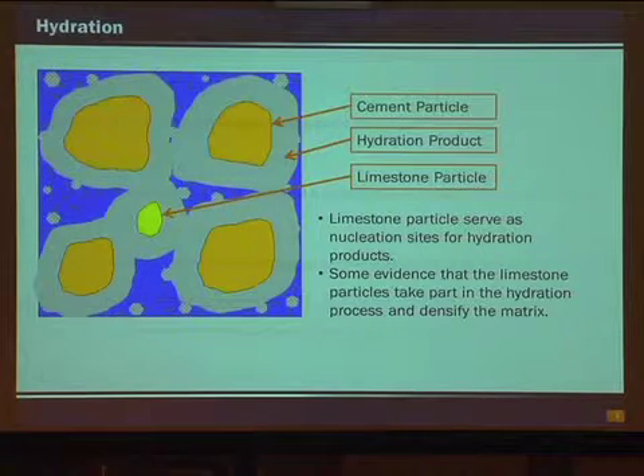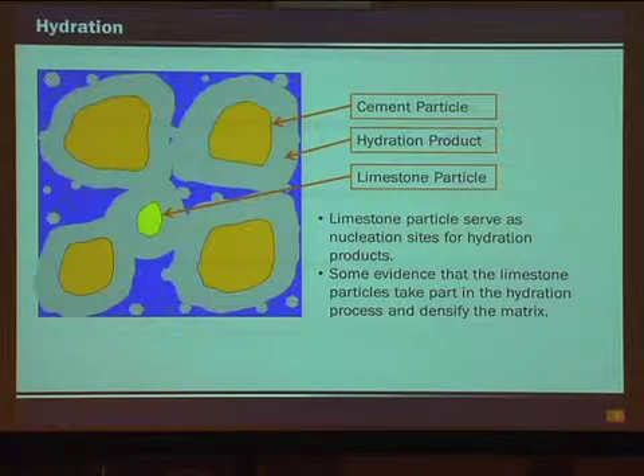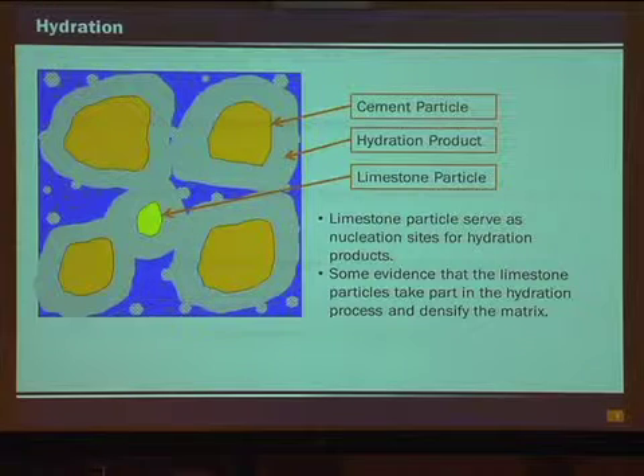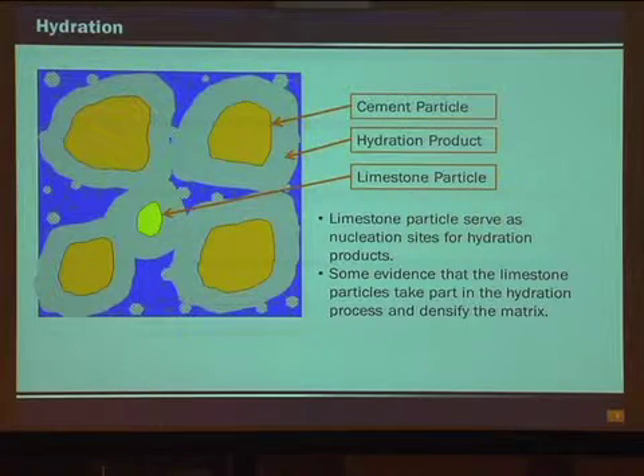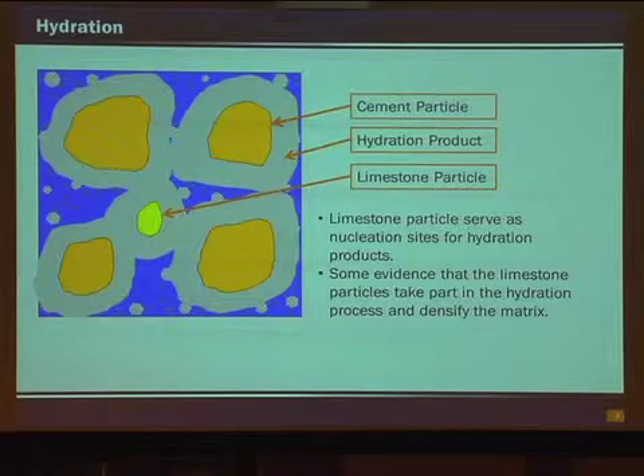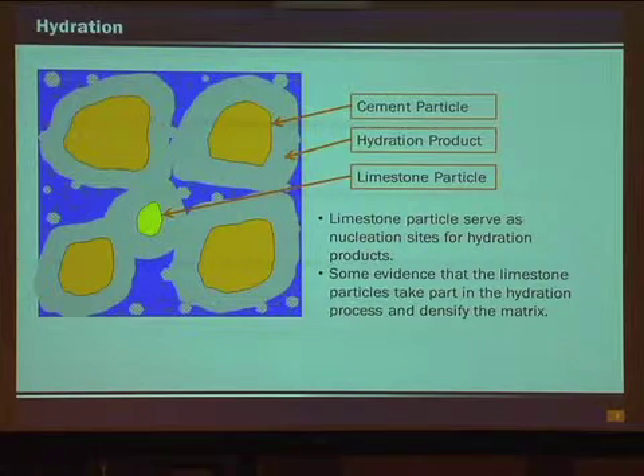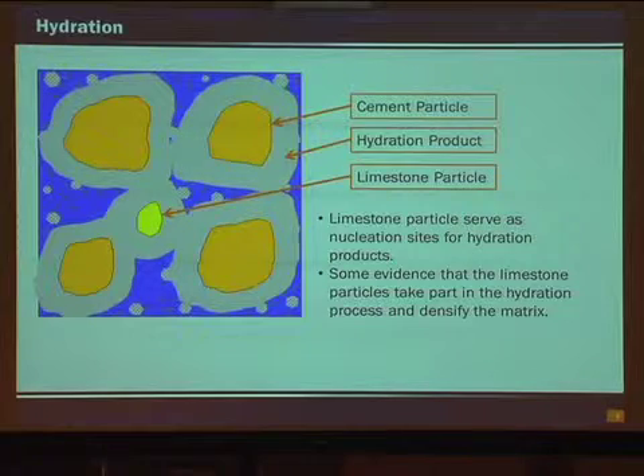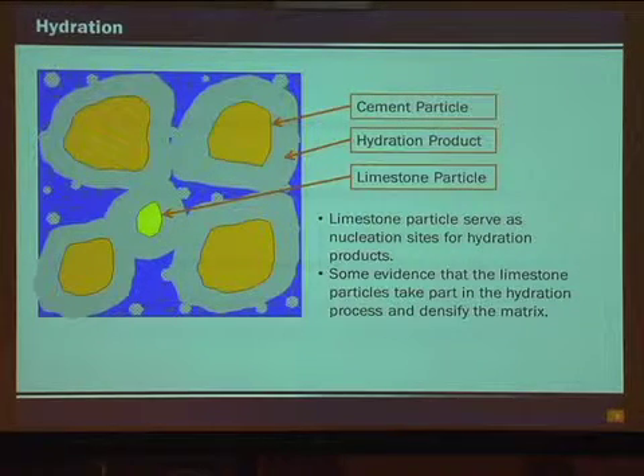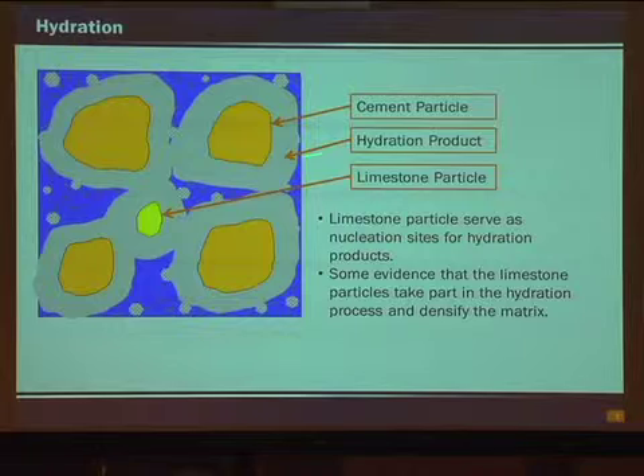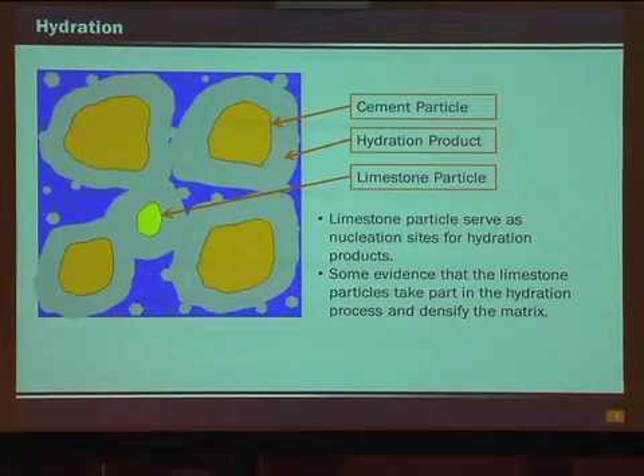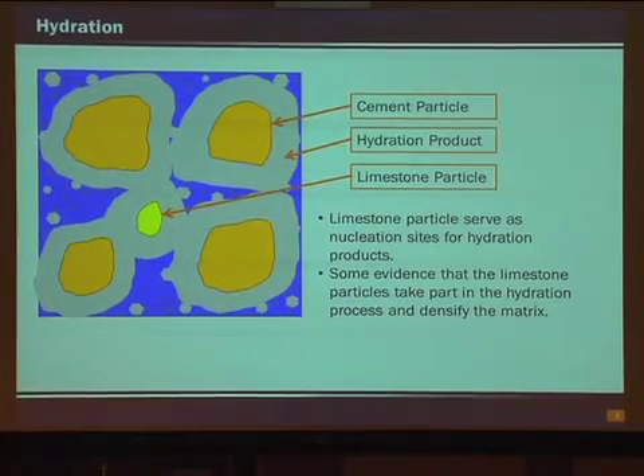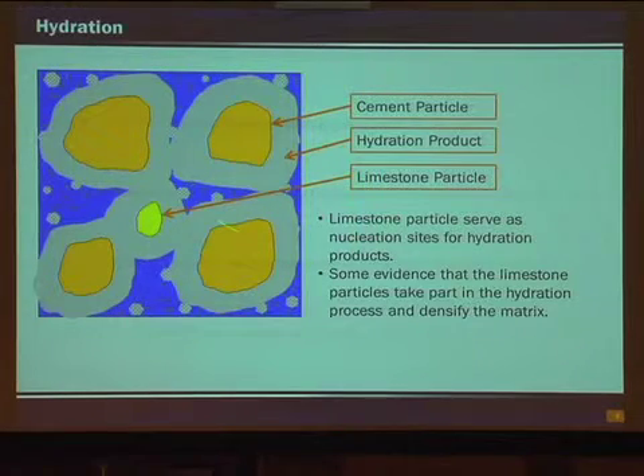Now there is some evidence that the limestone particles do participate in hydration. They react with the aluminate phases of cement and produce carboaluminate, which may or may not have strength or setting properties. That's still debatable. But there is some evidence that we do stabilize ettringite and improve the pore structure of the matrix of the paste and increase strength. So that's one of the benefits that people are seeing when using Portland limestone cements.